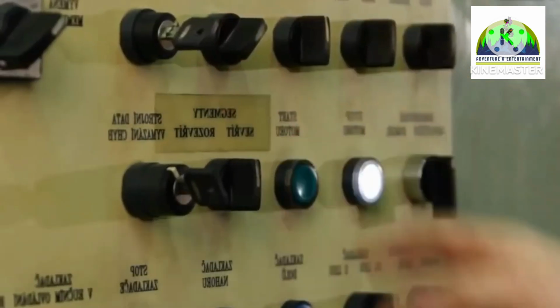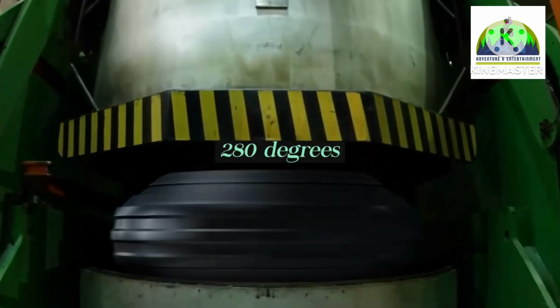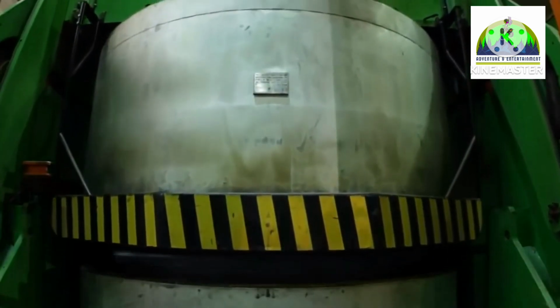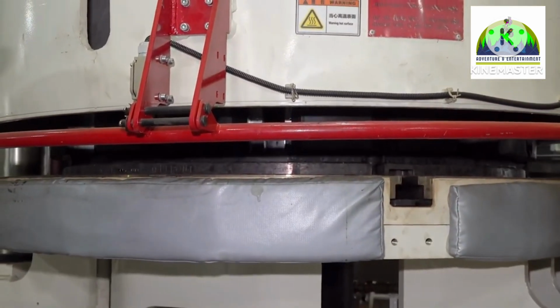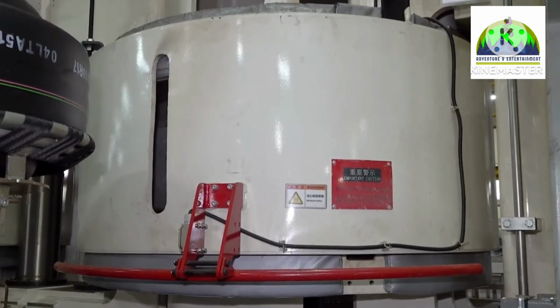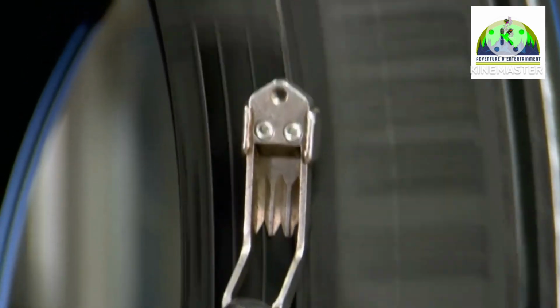During this curing process, the steam heats the green tire up to 280 degrees. Aside from the molding, the time in the hot pressurized mold causes the rubber to vulcanize, a chemical reaction that transforms it from a weak, sticky substance to one that's strong and elastic. After curing, excess rubber is trimmed away, leaving a clean and smooth tread surface.